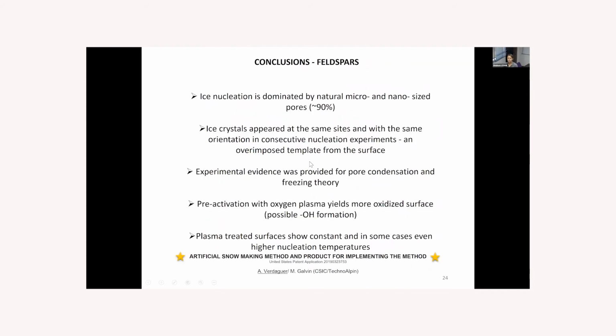So to conclude, the most important is that we could visualize and find out that the ice nucleation is dominated by natural micro nano-sized pores. This is 90% of the nucleation events we could count. Ice crystals appear at the same time with the same orientation in consecutive nucleation experiments, which may indicate an imposed template from the surface. Experimental evidence was provided for condensation and freezing theory.